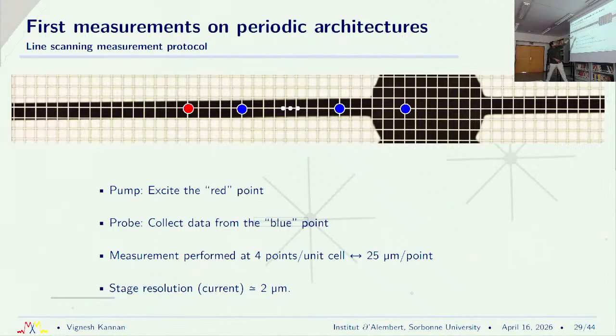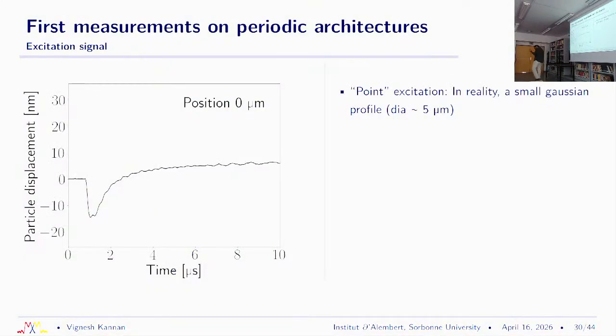So we did an excitation at this point. We did a line scan. Like I said, the unit cell dimension is 100 micrometers. So we did 4 points per unit cell. So we have a resolution of about 25 micrometers, and so we basically scanned about 20 unit cells in this experiment. And that's really a very, very small region of our entire sample.